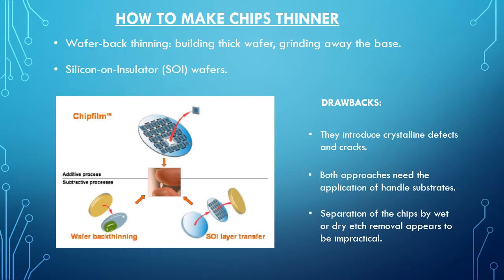But both these processes have their drawbacks. Grinding and dicing introduce crystalline defects and cracks at the edges of the wafer. Both approaches also need handle substrates to provide mechanical stiffness and stability. The device is bonded and then debonded to these handle substrates. And the separation of the chips from the handle substrates by wet or dry etch removal appears to be impractical because of the high aspect ratio of the etching path underneath the chips.